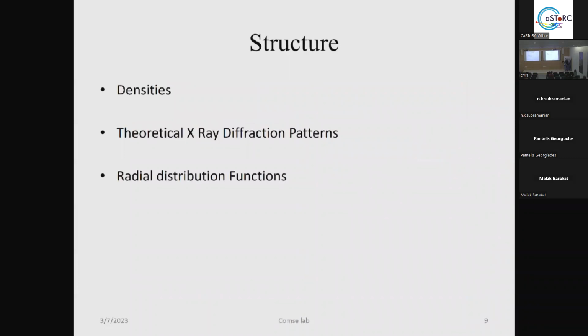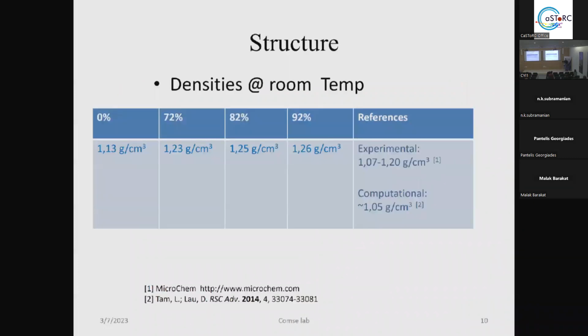And after that, we calculate the structure of the system. First of all, we show the density, how it goes as we increase the cross-link degree, and as we expect, it becomes more dense because we have a more glassy system. On the right, you can see the experimental values here.